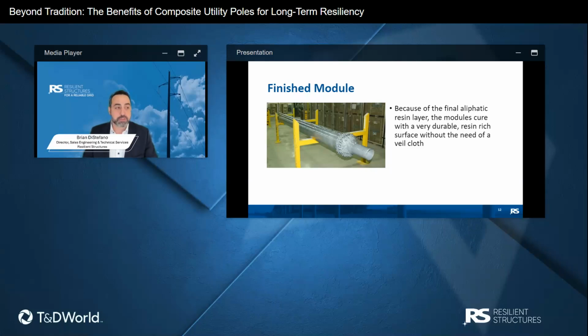The reason for that is in pultrusion processes, a veil cloth is typically required to achieve a resin-rich surface, which prevents fiber blooming, and it also gives the pole its outer layer of strength for damage. So our manufacturing method inherently produces a resin-rich surface without a veil cloth being necessary. So we don't need to add a veil cloth. The final resin-rich surface, with all that aliphatic resin, provides the finished surface. That's actually a pretty common question that we get.